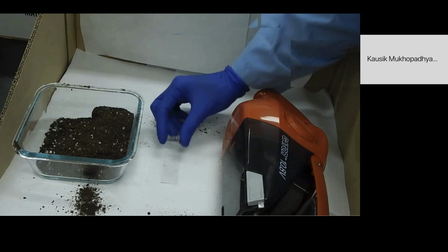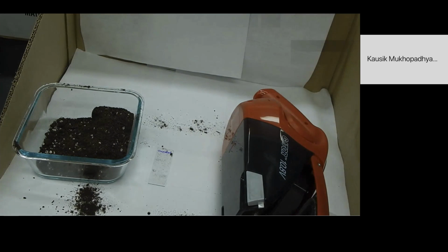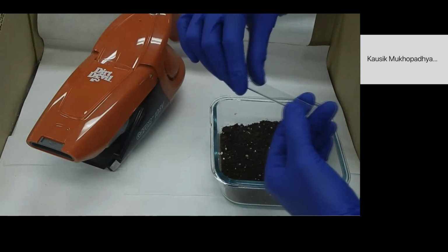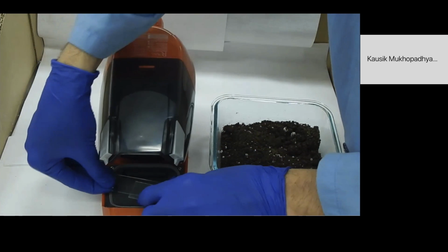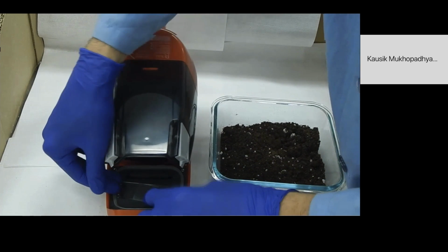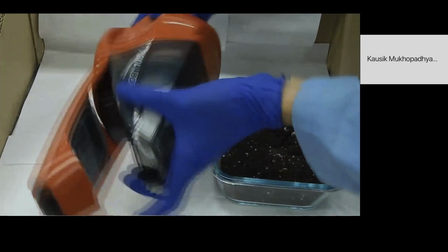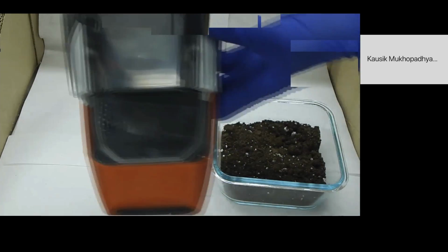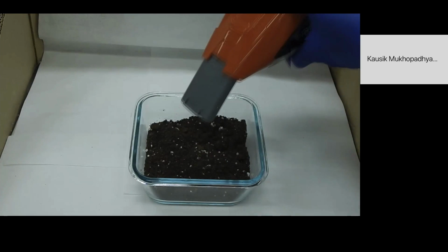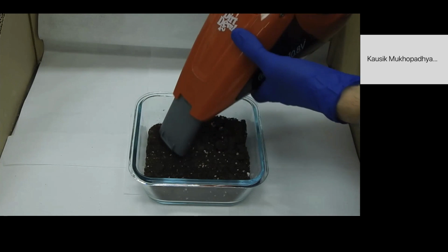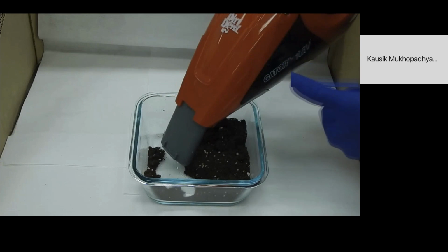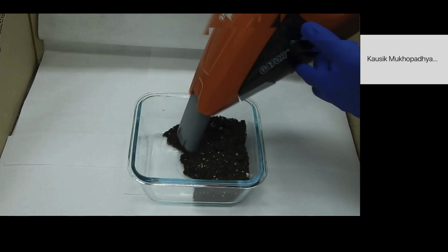What we did here is we actually used polymerization of silane molecules in the presence of water. And once they became polymer brushes, we also wanted to make sure these are durable, because there are many coatings out there which are not durable and they fail in durability. And that's where we actually created these brushes.